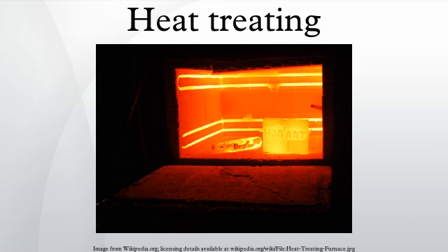The oxide film will also increase in thickness over time. Therefore, steel that has been held at 400 °F for a very long time may turn brown or purple, even though the temperature never exceeded that needed to produce a light straw color. Other factors affecting the final outcome are oil films on the surface and the type of heat source used.